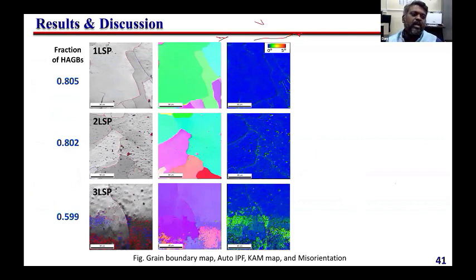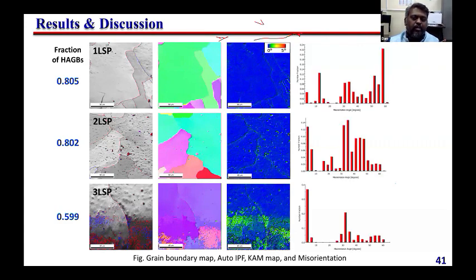Okay, three component system. For example, you see here, when you are doing one shot of laser shock peening, there is no such difference. When you go with two LSP, some dots are there, that is basically a refined structure. But when you go to three cycles of LSP, a large amount of low angle boundaries are formed. It means there is large refinement and strain formed. Because of that, we could get a different property out of it.